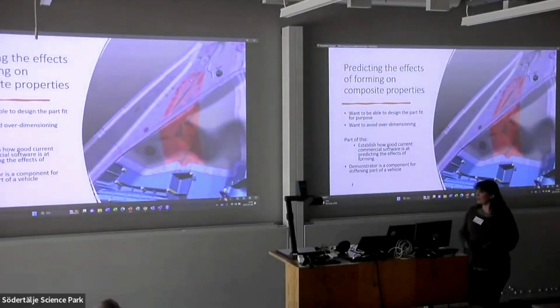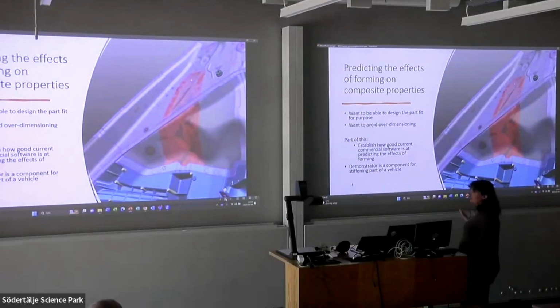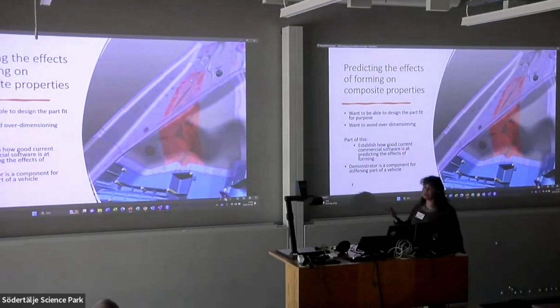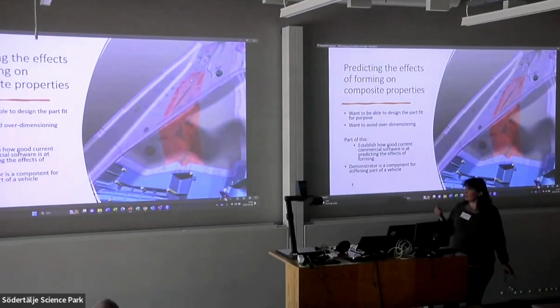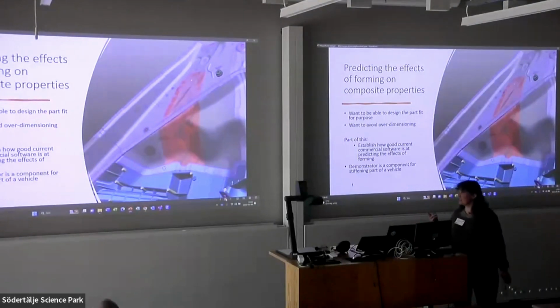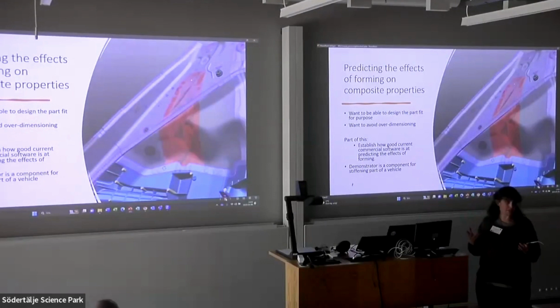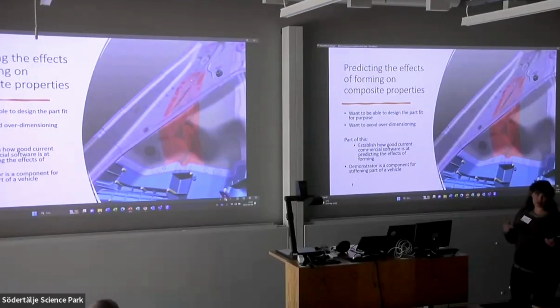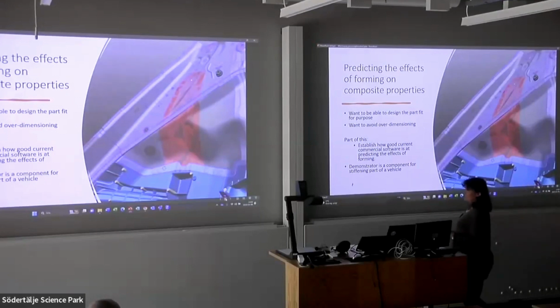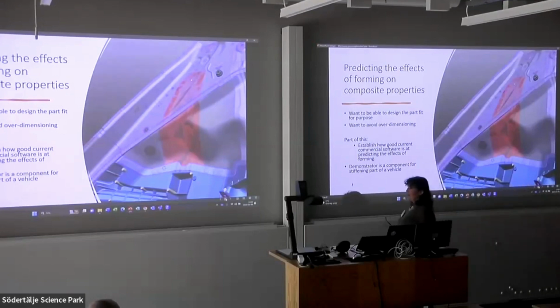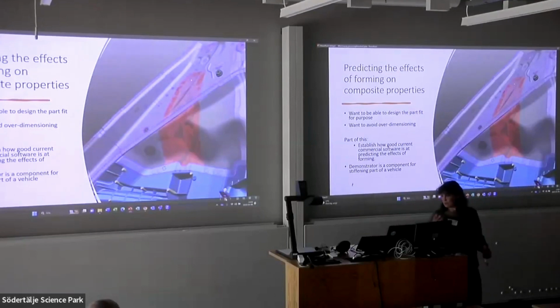What we're looking at here is predicting the effects of forming on the composite properties. And what we really want to be able to do is to design the part to fit the purpose, and we want to avoid over-dimensioning. So we have new models being developed, and that was done by LTU, stamped together. But we also wanted to see how good the current commercial software is at predicting the effects of forming. And then we have a demonstrator that was chosen by Volvo.